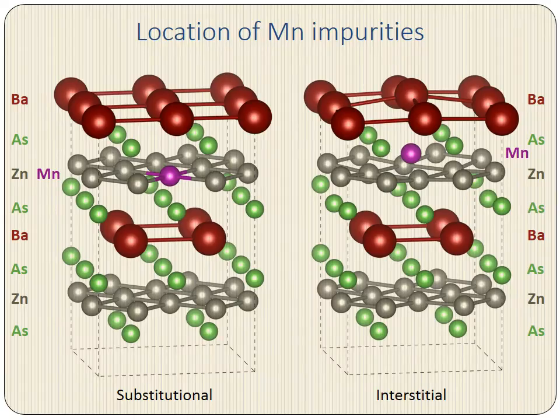To begin, we consider the case of manganese impurities. The following are relaxed structures obtained via DFT for a substitutional manganese impurity and also an interstitial manganese impurity. To figure out which configuration is more energetically stable, we cannot simply compare the total energy calculation for each supercell. Note that the number of atoms in each cell is different.